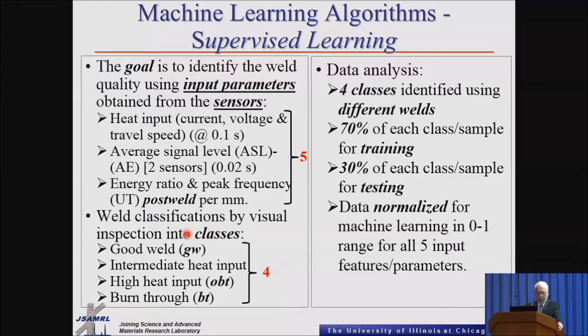As we discussed before, we needed to classify the different types of welds that contain the defects. The classes of welds that we had, remember, were a good weld, the intermediate heat input, which gave better penetration, then the high heat input or onset of burn through, and then the burn through. So in the data analysis, we identified 4 classes of welds.